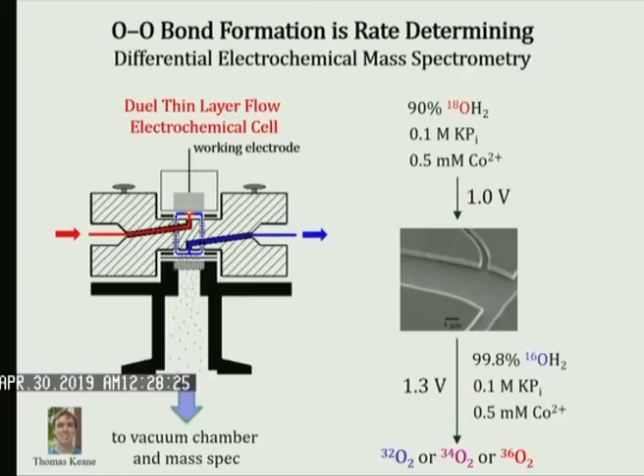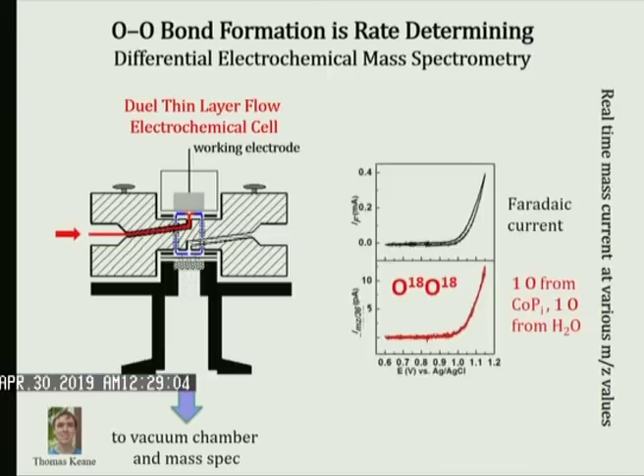And so what Thomas did under Sandra's program, we built an electrode. So here's your electrode that I can put a voltage on it and start generating oxygen. So say seawater comes in here in the red stream, it hits the electrode. We oxidize water to O2. The O2 gets entrained, so we made a little microfluidic device. The O2 gets entrained and comes over to here, it flows down here, and here's a membrane that we interface to a mass spectrometer. And so now what Thomas is able to do is, instead of looking at current, he can just put the mass spec at, say, the mass of oxygen.